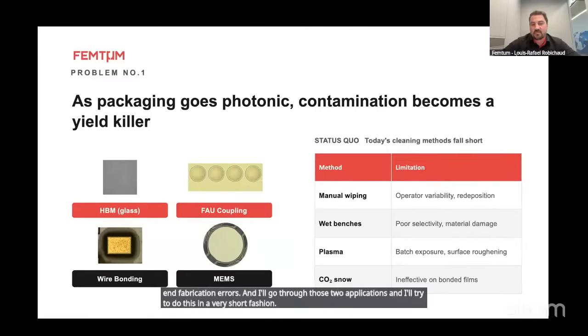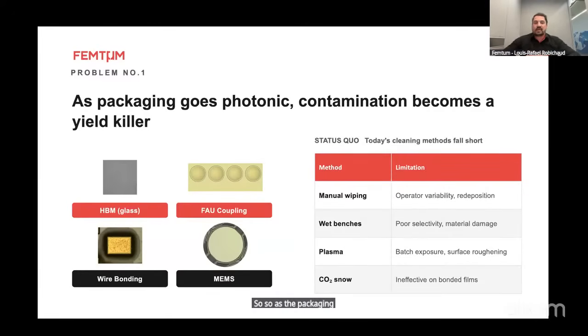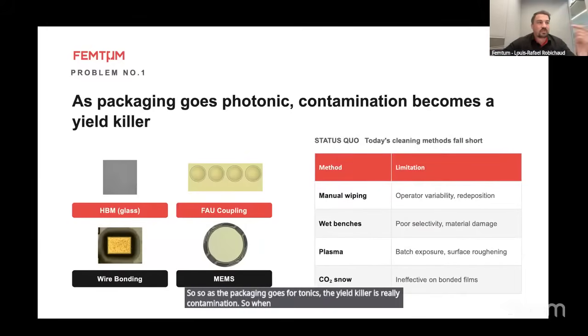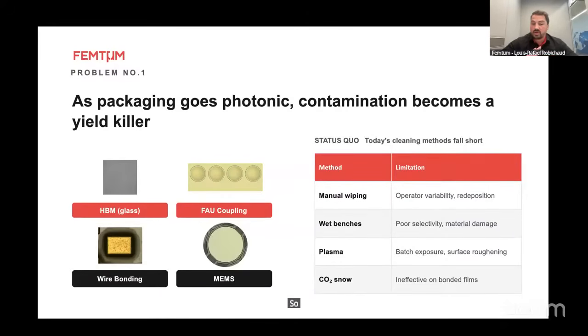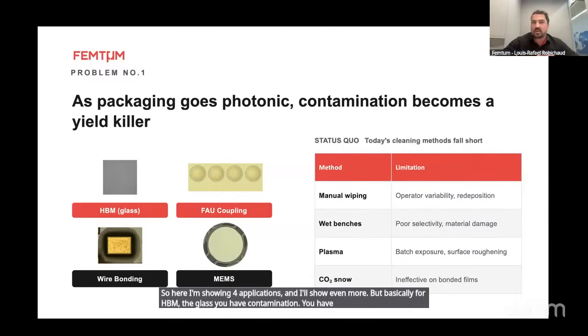As the packaging goes photonics, the yield killer is really contamination. When you dice, when you do bonding, when you do pick and place, when you do all these steps at the OSAT, these things contaminate the dies and the packages. Here I'm showing four applications, and I'll show even more. For HBM, the glass, you have contamination. You have FAU and the FAU coupling. You have wire bonding bleed outs. You have optical MEMS with the small mirrors. Anytime you have contamination on those surfaces, which I would call critical surfaces, you can kill the chips.